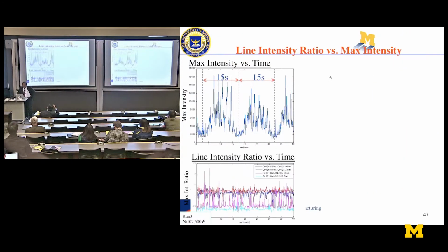Now another question my colleagues started asking: there's a lot of fluctuation of the emission plasma. How do I know I'm accurate? At 10 milliseconds the intensity will probably be high, and then after a few milliseconds, the intensity is low. How do I know how accurate or stable that calculation is? So what we found is, when you take the line intensity ratio, it becomes very stable. So instead of looking at individual lines, we are always normalizing a line with another more powerful atom's line.